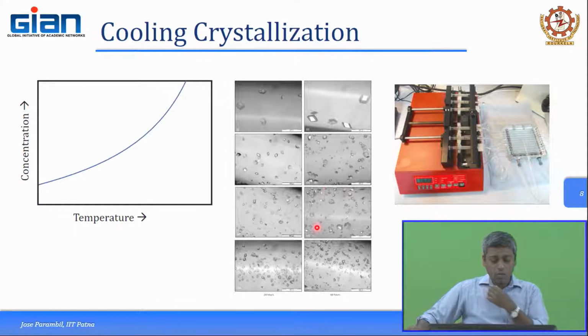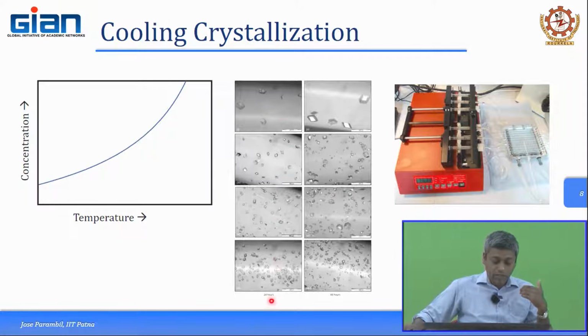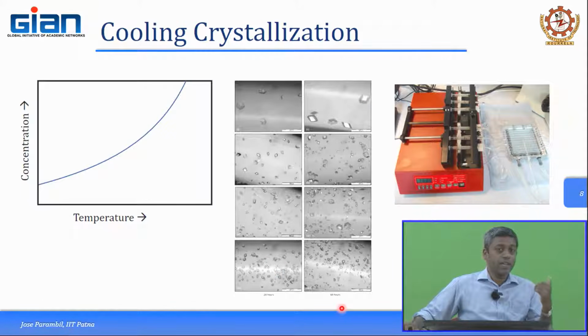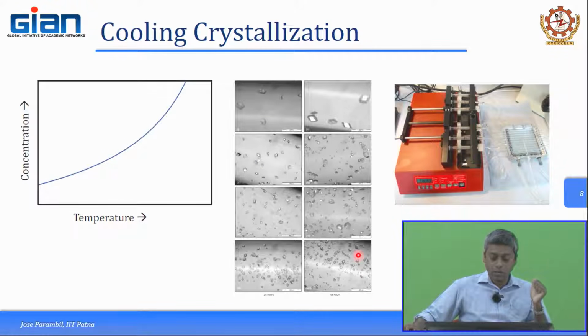And this study was conducted in order to figure out what is the impact of shear in crystallization process, in protein crystallization. And so, these are different, this is for 24 hours, this is for 48 hours. So, you can see that for 48 hours we can continuously do the crystallization process as well. So, it can be a continuous or a semi batch sort of process that we can do. And with shear, with varying shear.